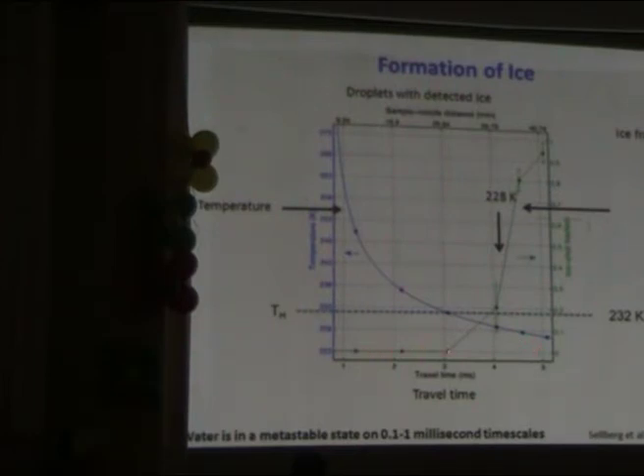Here's the fraction of shots that contain ice, respectively water. So we see no ice crystal until we are well below the temperature of homogeneous nucleation. But even at 227 Kelvin, we still have a fraction of the order of a few hundred droplets that have remained liquid at 227 Kelvin. So what can we extract from this?